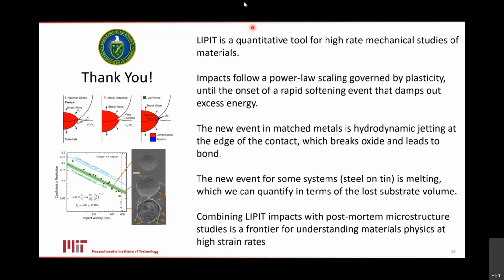Yes, so this is another thing I didn't have time to show, but we did a whole giant body of work in aluminum. Aluminum has a thin and very tenacious oxide layer, and we studied different aluminums where we intentionally changed the thickness of that oxide layer. And your question is dead on. If we use materials with thinner oxide layers, we get earlier bonding transitions. It's easier to break them when they're thinner.